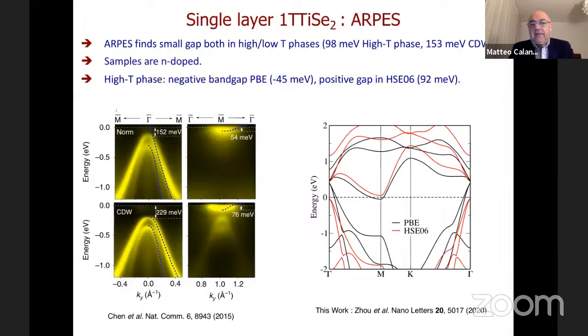Of course, the first thing that one can try to do is to calculate the electronic structure for the 1T phase. As you can see, if you do a PBE calculation, a standard density functional theory calculation with the generalized gradient approximation, the two selenium bands at the gamma point are not completely occupied, and the titanium D bands at the M point are partially occupied. So this is in disagreement with experiment.